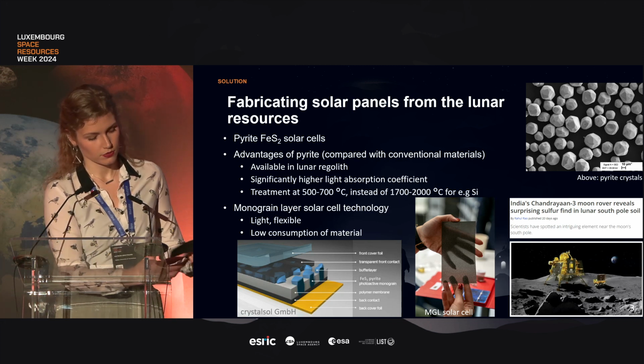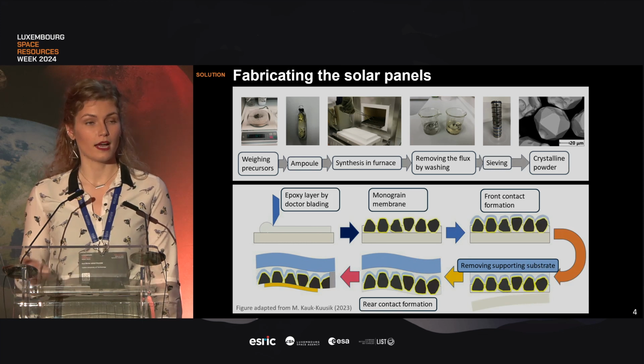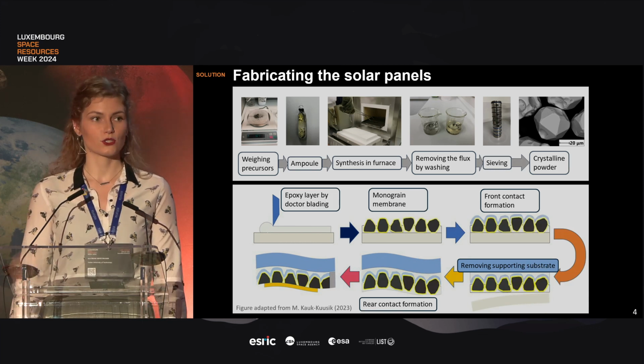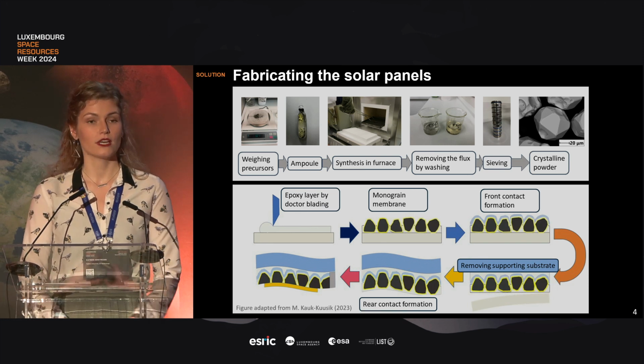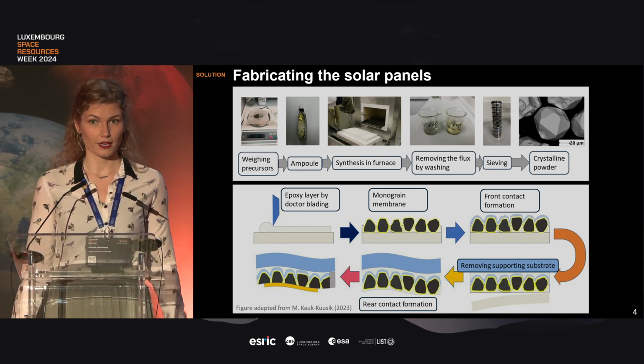So that's what we do. Our solar cells look like this. They are thin, lightweight, and flexible. You can take a closer look later with me. This is called the monograin layer solar cell, and the fabrication of pyrite monograin crystals starts with synthesis in quartz ampules in 500 to 700 degree furnaces. Then, after heating for several days, the crystals are removed from the ampules, washed, and sieved into narrow size fractions that are then used in fabricating the monograin membranes.